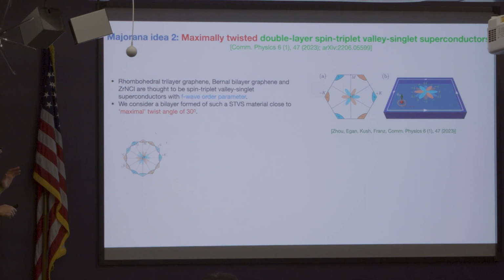So in this case, it turns out the calculation is quite a bit more complicated than in the case of cuprates, precisely because these small Fermi surfaces are centered at the corners of the Brillouin zone. So one has to do a sort of Bistritzer-MacDonald type analysis with superconductivity on top. So one has to really consider properly all the scattering wave vectors, and so on, to solve this problem.